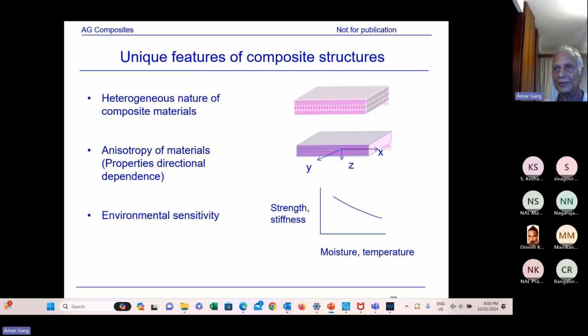In composite, that is not so. Through-thickness stiffness and strength is very low. Then another thing is environmental sensitivity. Strength and stiffness degrade with moisture and temperature, although stiffness does not degrade significantly compared to the strength. It doesn't happen with metals. Metals degrade only at very high temperatures, but at normal temperatures of operation, there is no significant change in their properties.